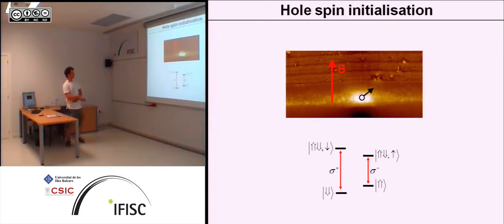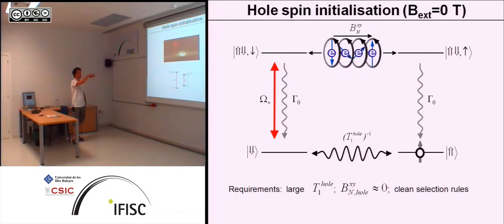So how do we do this experiment? Here we have the four-level system of a hole spin in the quantum dot. The quantum dot is charged with a single hole. In a magnetic field, the spin can be up or down, and this energy difference is the Zeeman splitting. We can now excite with circularly polarized light, sigma plus or sigma minus, and create this exciton where you have an additional electron-hole pair. Here you now have a spin singlet for the holes and an additional electron spin down or spin up. In this experiment, the magnetic field is applied along the growth direction.